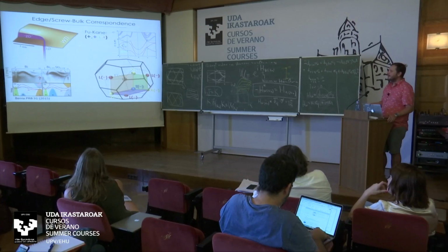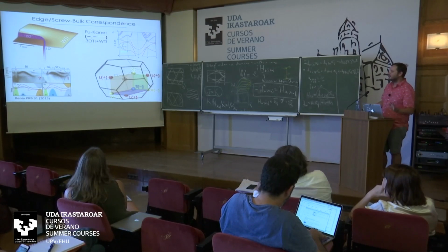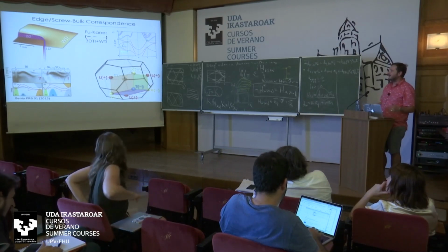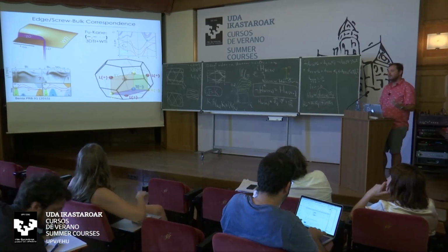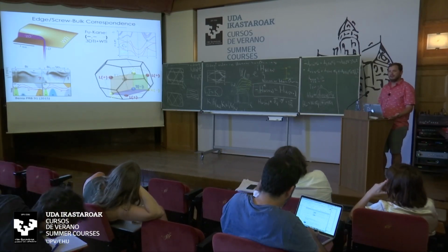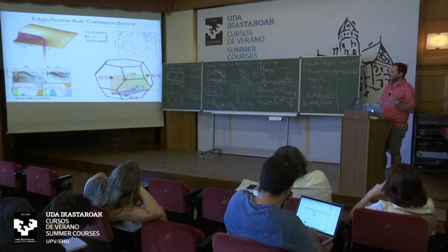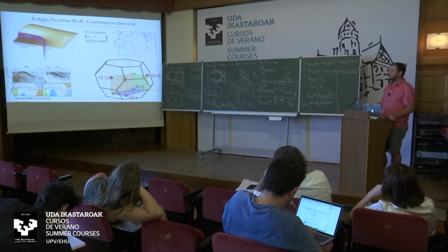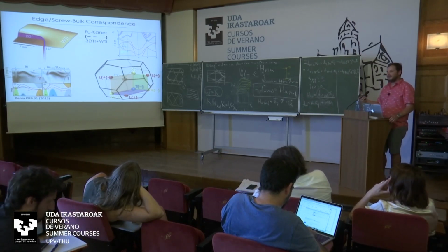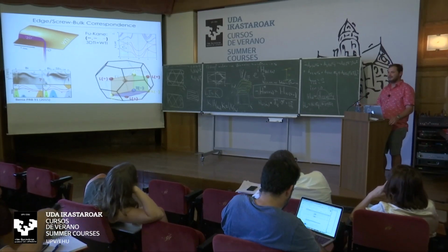It is somewhat uncertain from experiment, and of course it is important to observe that if we would invert our known order of the bands around L, we would get a strong topological insulator with weak indices, which would support the kind of behavior that we see in experiment. But actually what we think is that we don't even have to invoke such an inversion or uninversion that DFT never reported and observed.